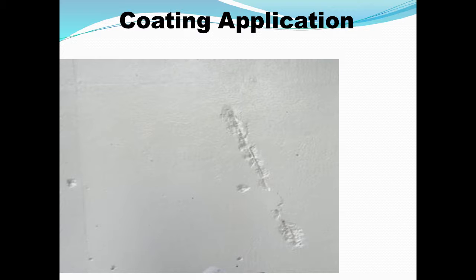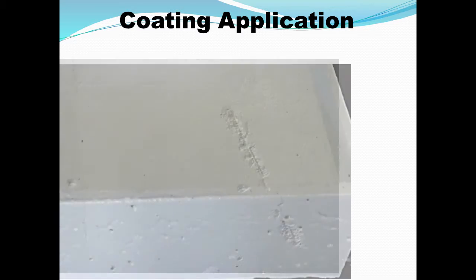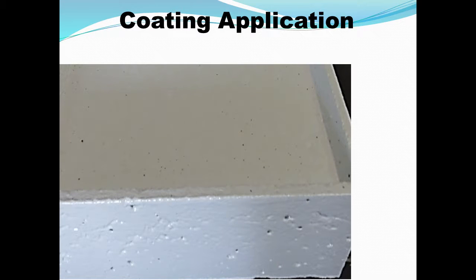And you can see in here, it's sort of tough to see at this angle, but there's some areas in here that had pinholes. And in fact, this is the salt ponding block that was cast in the lab. And as you can see, there's a fair number of pinholes in it. I understand that that will allow the salt water a path into the concrete, but our assumption was if it doesn't apply easily and wet easily and fill these up in the field, it's probably not going to happen anyway. So we want to know how your coatings perform with the type of application that it's likely to get.